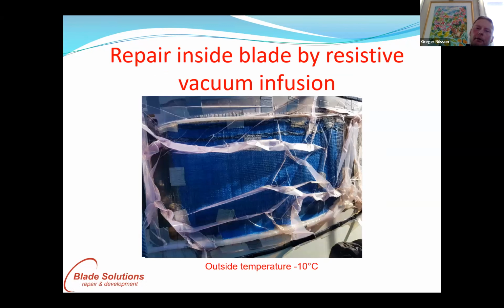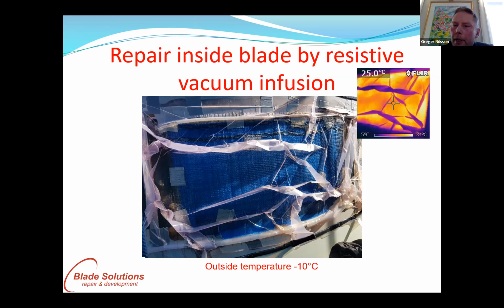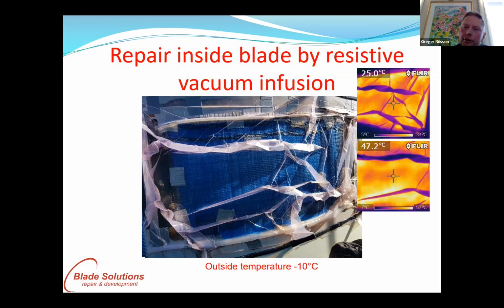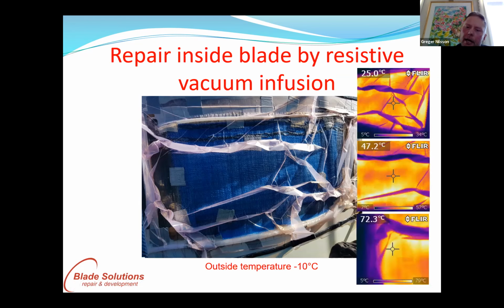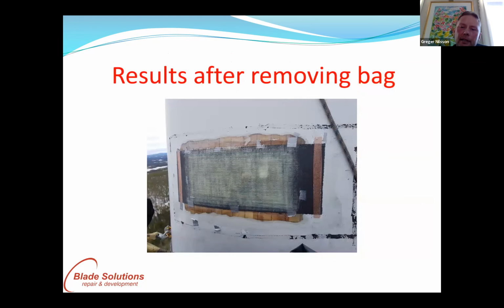This is where we do the vacuum infusion. And here to the right, you see the temperature during infusion. We have 25 degrees. And after the infusion, we increase the temperature for the curing. So we have around 50 degrees for the curing, and we end up with a post-curing process where we have 70 degrees. This is the result. You can see the connection points to the carbon here, and here you have the repair patch.